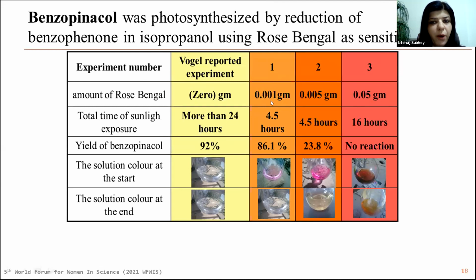In experiment number 1, we added an amount of rose bengal of about 0.001 gram. The time reduced to 4.5 hours with 86.1% yield. This reaction is followed by gas chromatography. In experiment number 2, we increase the amount of rose bengal to 0.005 gram. The yield of benzopinacol is reduced to 23.8%. When we increase the rose bengal concentration, the percent yield of benzopinacol formed decreases.